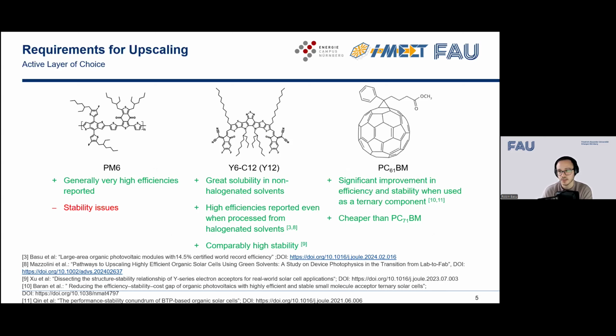So PM6, because in general, you get quite high efficiencies and there is a lot of research done on it, and also a lot of champion devices are made with PM6. However, it struggles a little bit in stability. The Y12 has great solubility, specifically in xylene, and even sometimes shows higher efficiencies in xylene compared to chloroform. And it is reported to be extremely stable. And actually, according to a paper by Zhu et al., it's even the most stable Y series NFA.